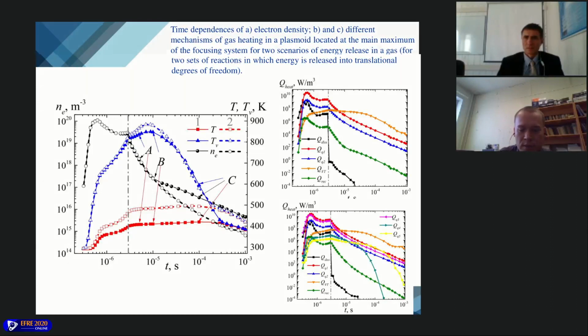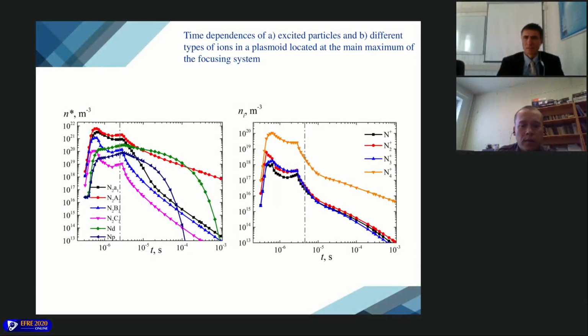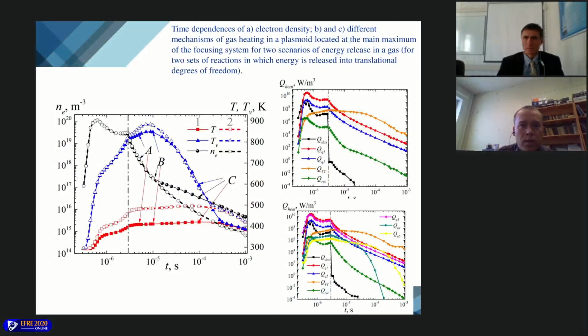The main gas heating channels for the 2 considered sets at different times are shown on these figures. In the case of the first set, the main gas heating channels during the first fraction of a microsecond of the active phase are the release of energy in self-quenching reactions of excited nitrogen particles.